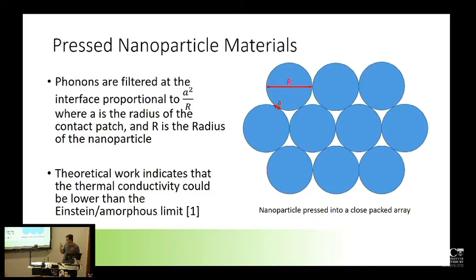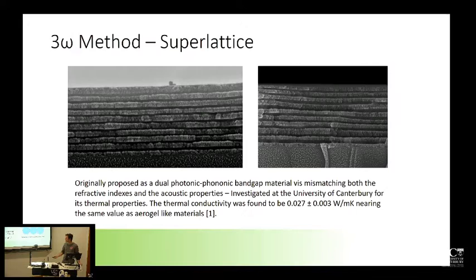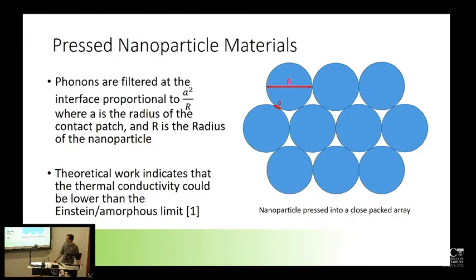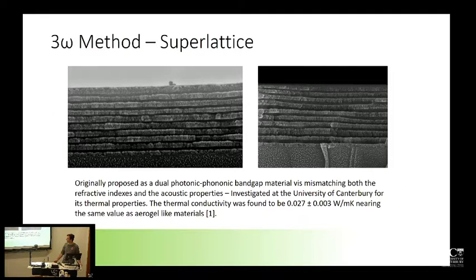So the idea is if it wasn't multiple coherent phonons in this structure, if it wasn't phonons traversing entire layers, perhaps an explanation for why the thermal conductivity was as low as it was is just the nanoparticle layers singly. Perhaps this value that we measured here was just a sort of average or distance average of the silica material and the relatively known thermal conductivity of PMMA.